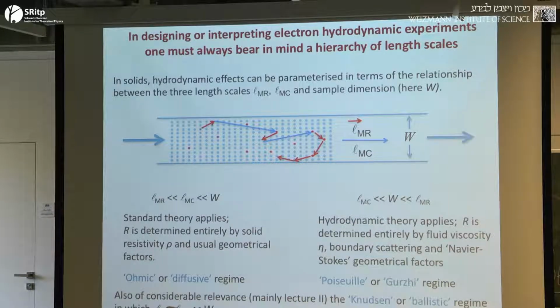Something which is really relevant is that the hydrodynamics of gases contains this Poiseuille regime, but it also contains what's called the Knudsen regime. The Knudsen regime in gases is when you've arranged a situation where the pipe that your gas is going through has a narrower radius than any of the microscopic scattering lengths in the system. This Knudsen regime from gas hydrodynamics is equivalent to what we usually call the ballistic regime when we're dealing with solids.